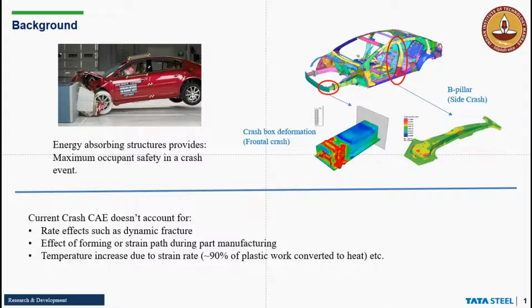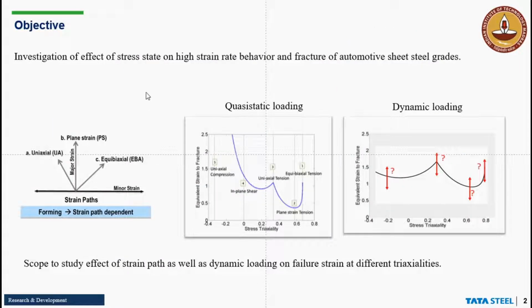and there could be temperature increase due to strain rate, and there could be local softening due to which the failure behavior of the part itself could be changed. So in order to study this, we need to investigate the effect of stress state on high strain rate behavior and fracture of the sheet which is used in automotive. So even before crash, there could be forming of the component as well, and there could be path dependence which could actually influence the crash.